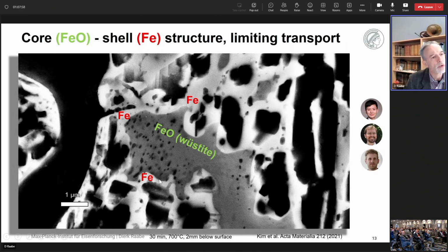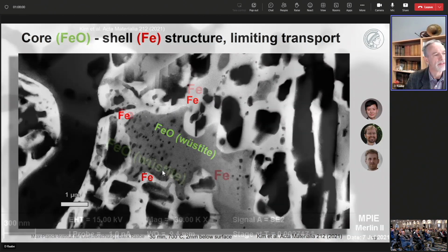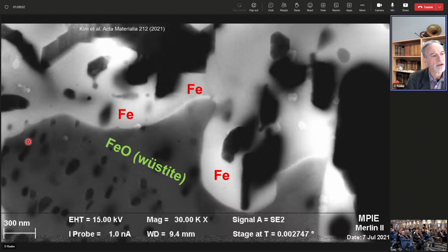And you see then, when we grow yet a little bit bigger, that you have on the inside this gray appearing FeO, the wüstite, which is a cubic material. And you see then again this film that you could see in the microscope just before, densely surrounding this Swiss cheese of the wüstite. Again, you have the oxygen vacancies collapse and form nanopores. The nanopores grow into micropores and so on. So I come back to those.